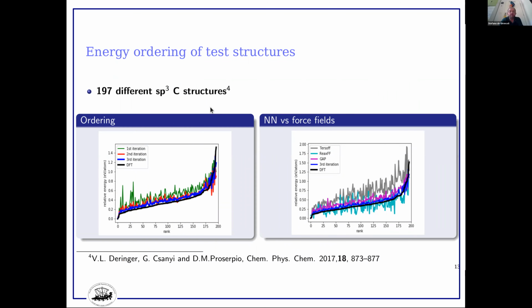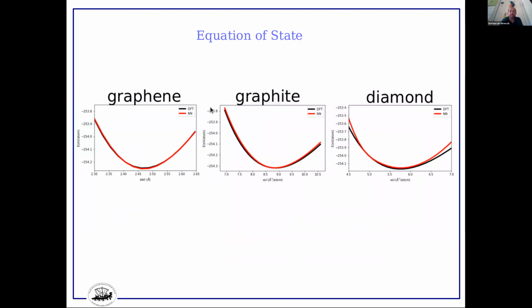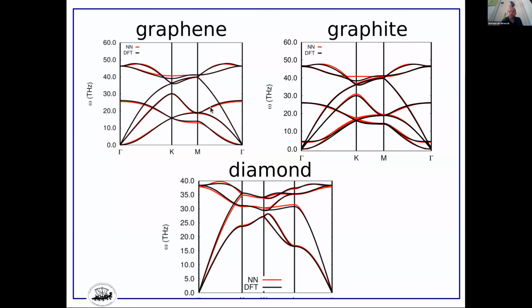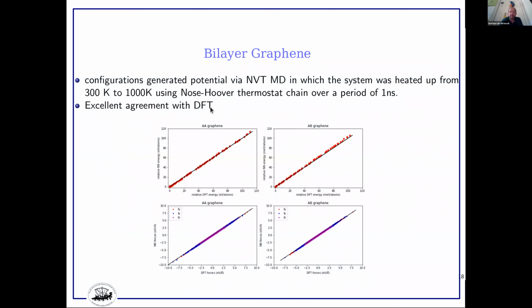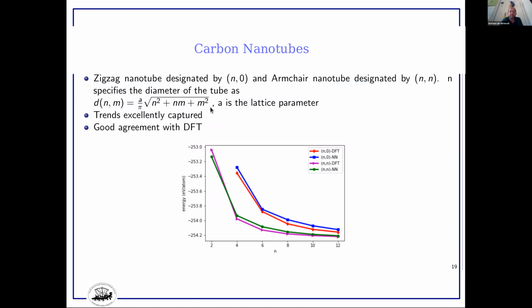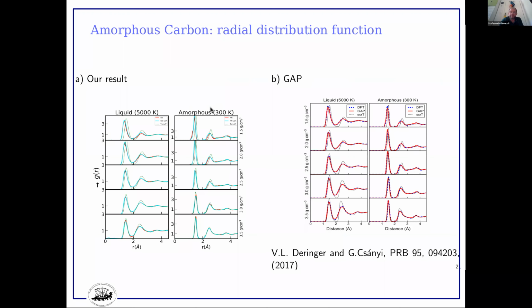We did a number of calculations and we saw that our potential was very accurate, comparable with the GAP potentials for carbon, for a number of carbon structures that were proposed in the literature. We get very good equations of state. We get very good phonon calculations for graphite, diamond, and graphene. And then there was more study on bilayer graphene and carbon nanotubes. The comparison with respect to DFT and neural network results is all very favorable. And amorphous carbon is also very well reproduced. The calculations compare very well with the experiment and with previous calculations by the GAP potential.